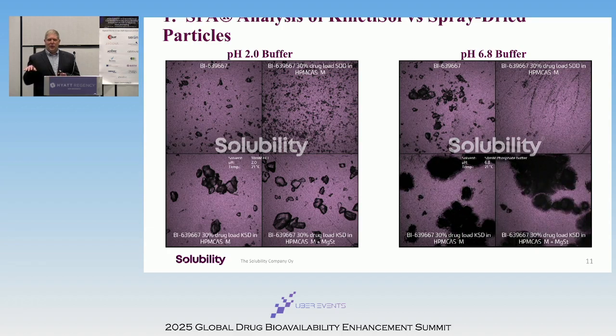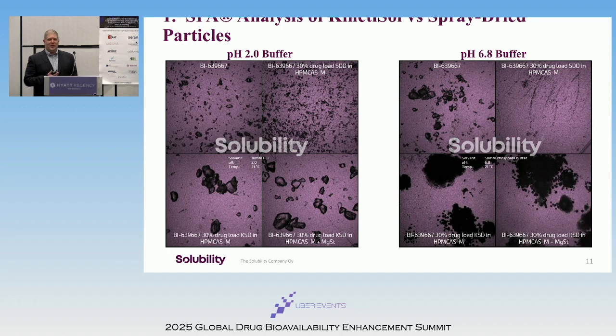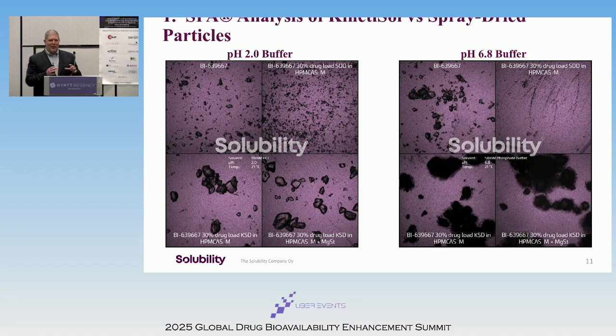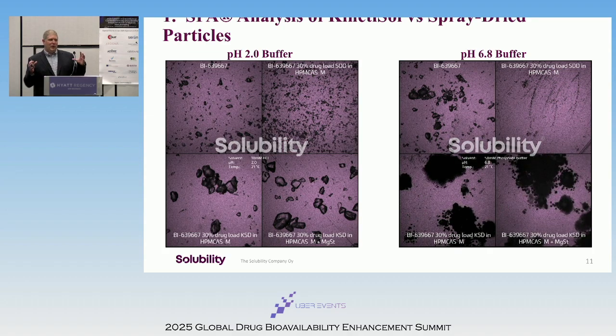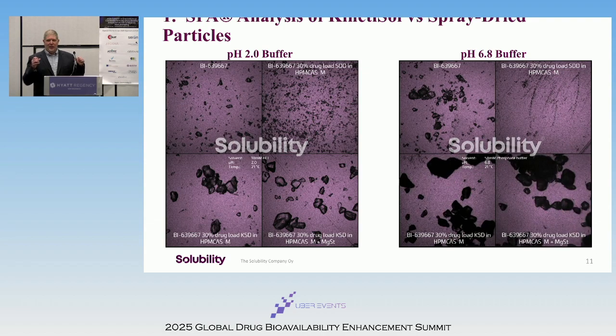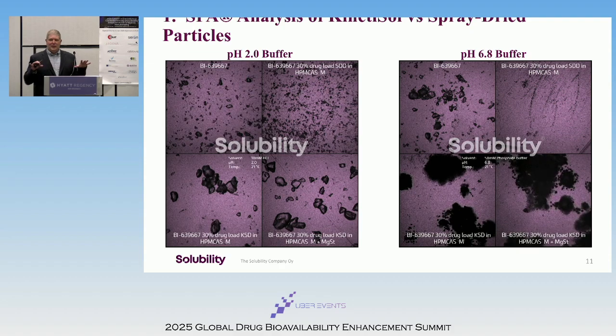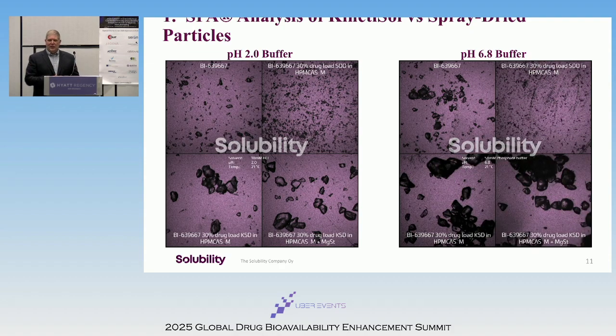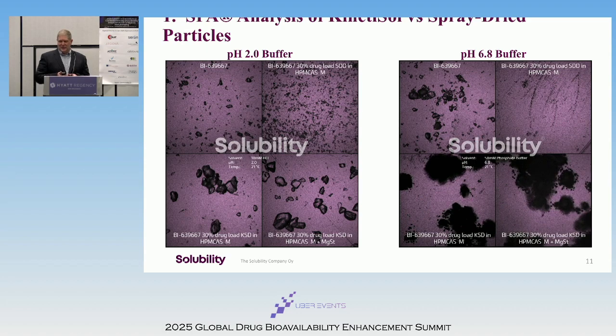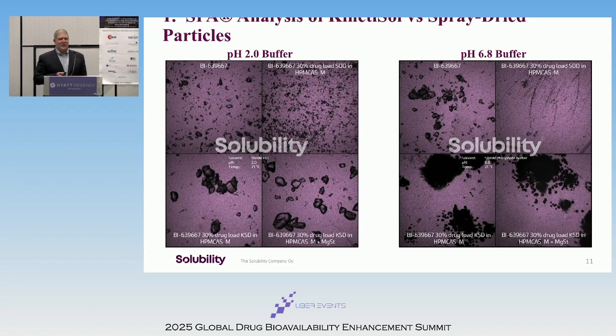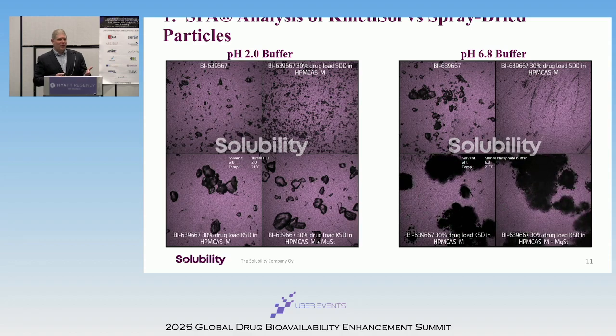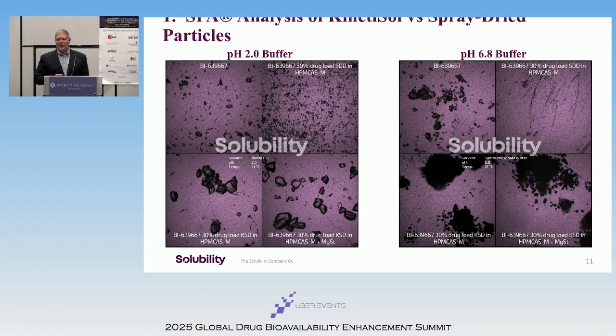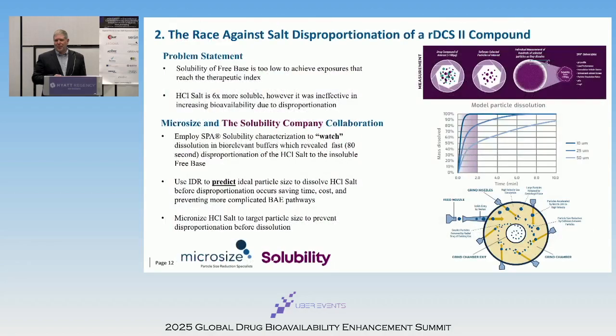On the bottom rows are the KinetiSol particles, where you can see they slightly swell at pH 2, but they behave totally different at pH 6.8. It's like an explosion of particles where the API is slowly leaching out in a sustained release mode. So with this technology, you can actually visualize what's happening with your formulation and see visual evidence of what's going on.